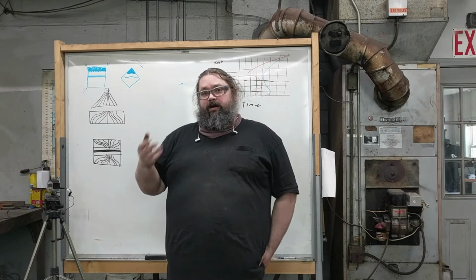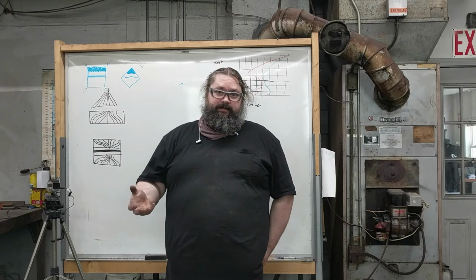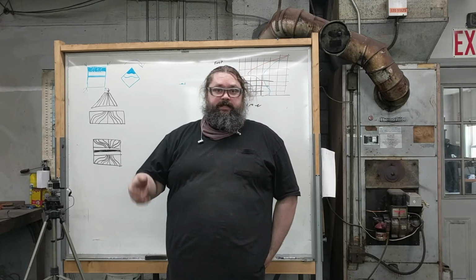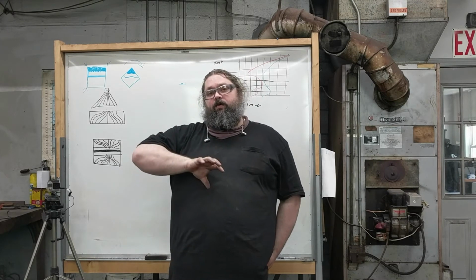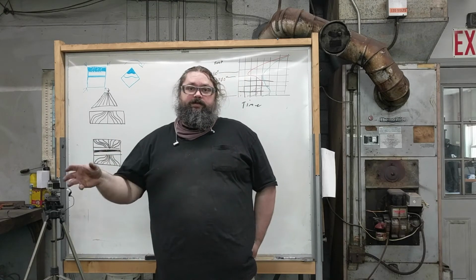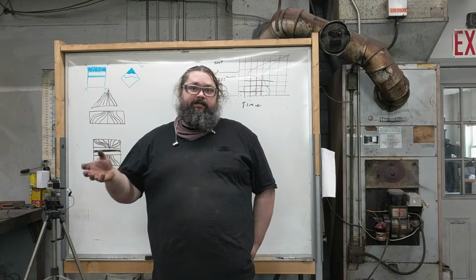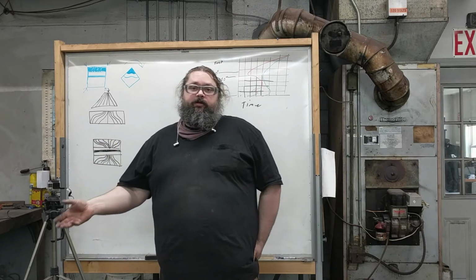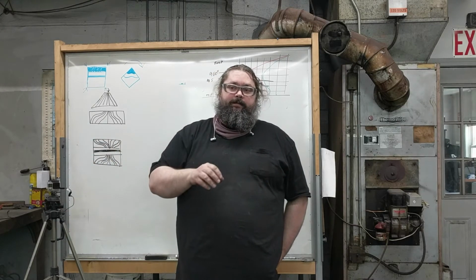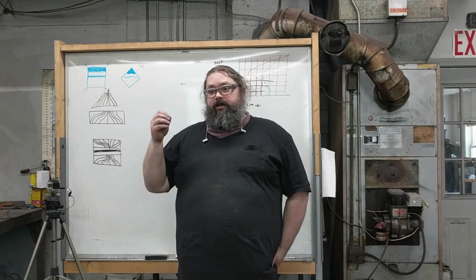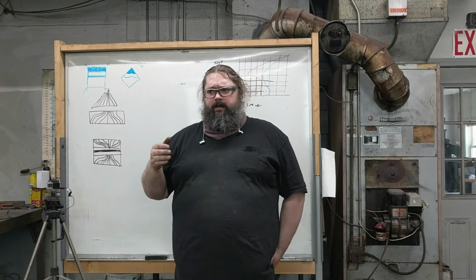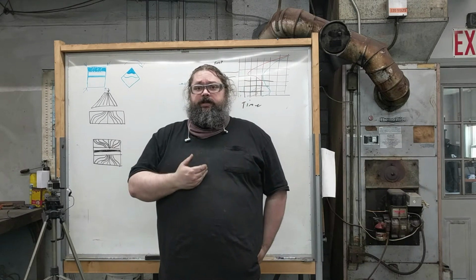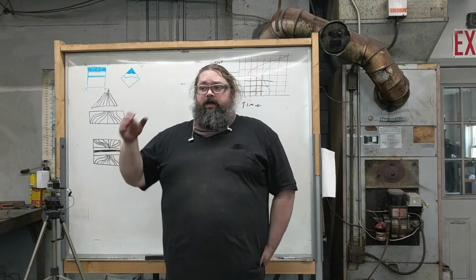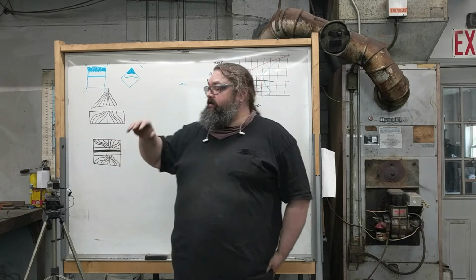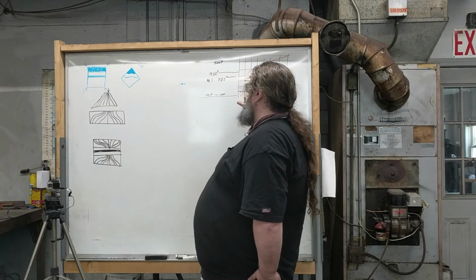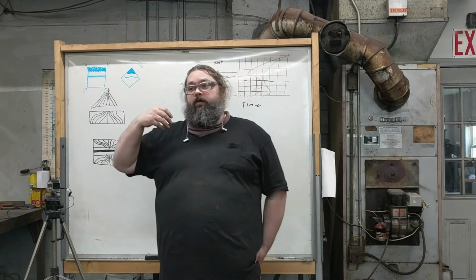And that's how you get austenitic stainlesses or non-hardenable stainless steels. Things like 304, 316. Those have so much nickel, they have forced that structure over so it's stable at room temperature. Hardenable steels don't have that issue, but they won't be able to turn over to martensite without this added step. What that means for us knife makers is that we need to bring the temperature down as fast as possible. I find if you quench in oil or plate quench with air and force that to the very fastest you can get this quench and try to cross this line instead of this line,